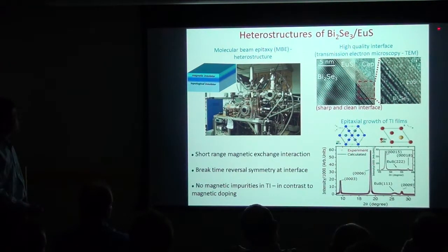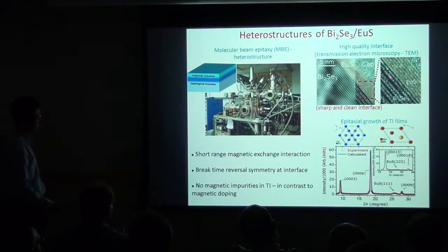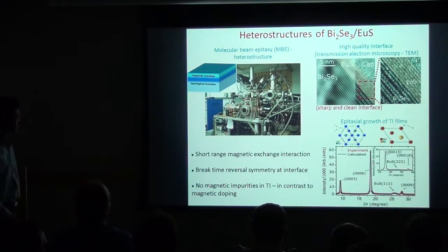For example, if we grow europium sulfide on bismuth selenide, this figure is a transmission electron microscopy image. Then you can see that the interface between bismuth selenide and europium sulfide is very sharp, and you can see the quintuple layer of bismuth selenide. And the other is the FCC structure of europium sulfide, and the interface is very sharp, and there are no impurities. This can also be proved by the X-ray diffraction